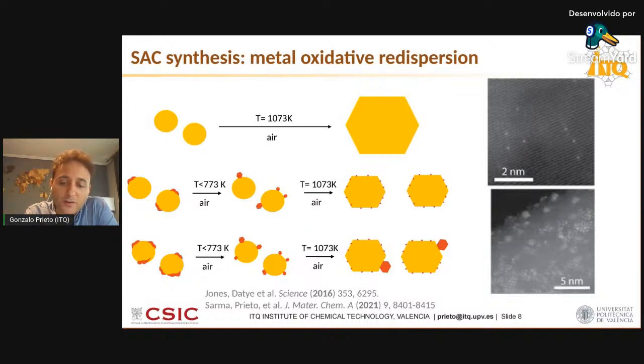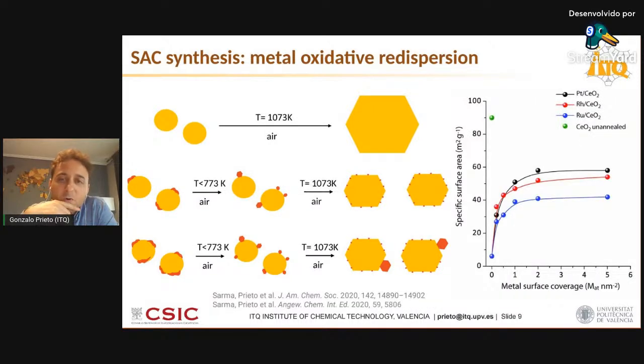Indeed, this saturation point beyond which stabilizing a monatomic species is no longer possible, at least in our hands, and for the series of all different 4d and 5d transition metals we have dispersed on a number of different oxides, happens at around 1 to 2 metal atoms per square nanometer. That's what this plateauing, this leveling off of the specific surface area versus the metal content, is telling us. Beyond there, the specific surface area is no longer increasing, meaning that we have reached the maximum stabilization we could have, and that translates into the fact that all anchoring sites on the oxide support have been saturated. Beyond those contents, metal agglomeration sets in.